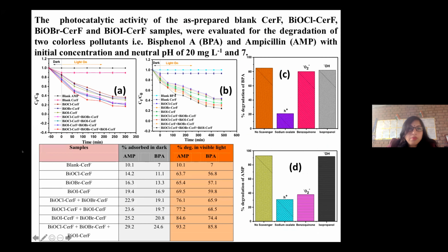Photocatalytic activity: when we checked the photocatalytic activity with only one immobilized Cl, Br, or I ceramic fiber, it was not much. If we took chloride, bromide, iodide in combination, then the activity was higher compared with the single one. So the thing is, we have to see how we can stop or separate electron holes as well, to enhance the activity. Adsorption was done, then degradation was done. You can see the results. 93.2% ampicillin was degraded in the presence of all combinations, and bisphenol A 85.8%. These are very difficult to degrade, but in combination they showed good results.